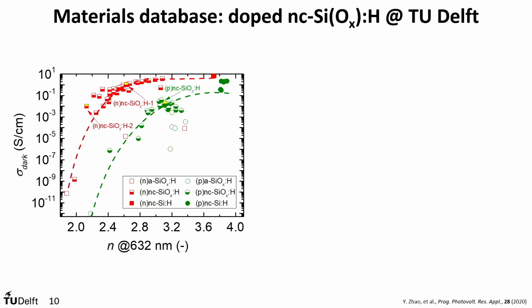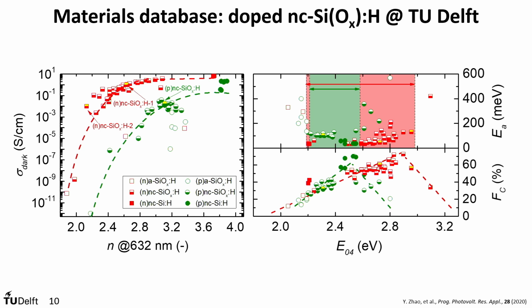So what we did already a couple of years ago, we changed massively, in a very large parameter space, the plasma conditions and gas mixtures in order to create a database of materials that could hit these very diverse optoelectrical properties that can then be used profitably in our solar cells. So for example, we went on looking into nanocrystalline silicon oxide, and in this case we could go for a relatively low refractive index that could help with the optics of the device as well. But also looking into the activation energy, we could get a number of suitable candidate materials with activation energies well below 100 millielectronvolts, as well as some that can go as low as 50 millielectronvolts.